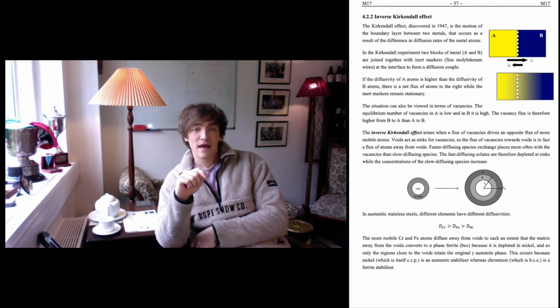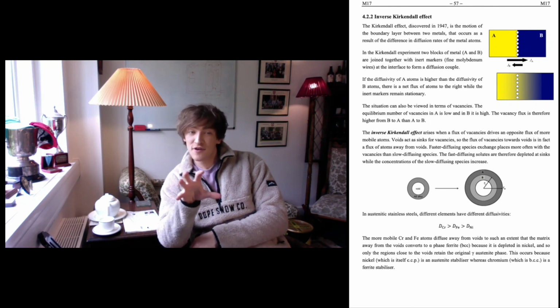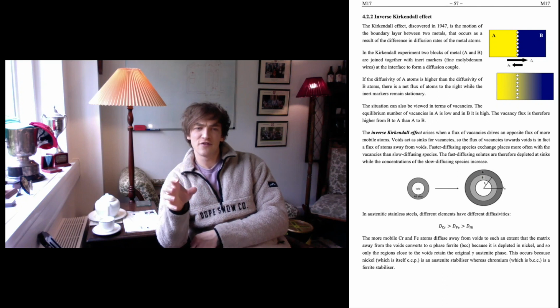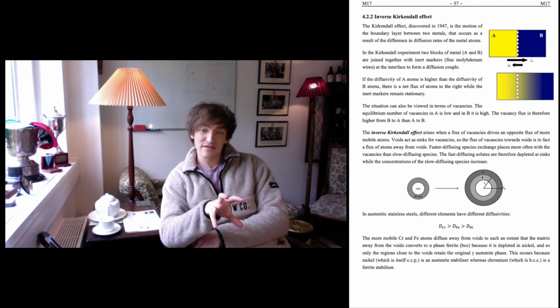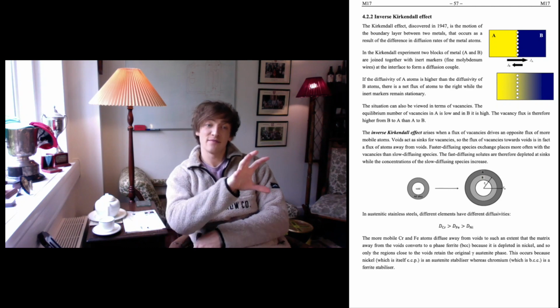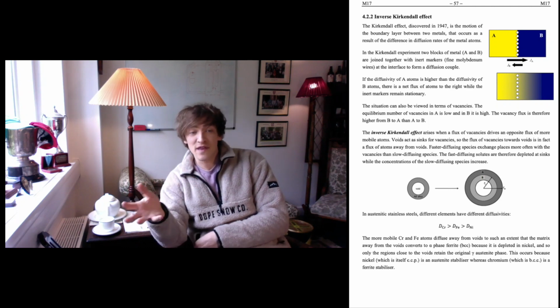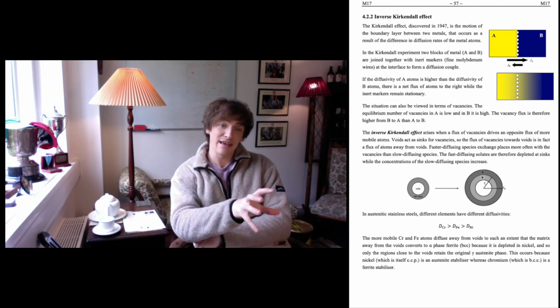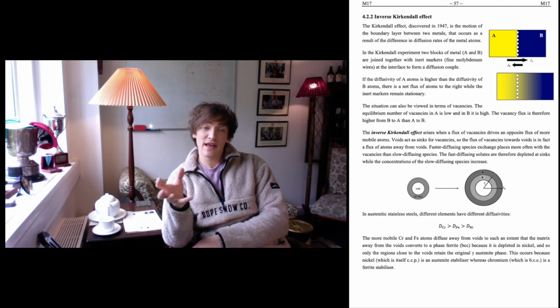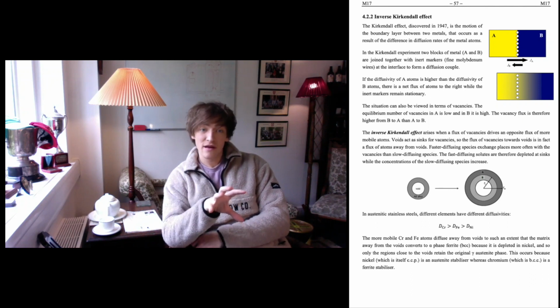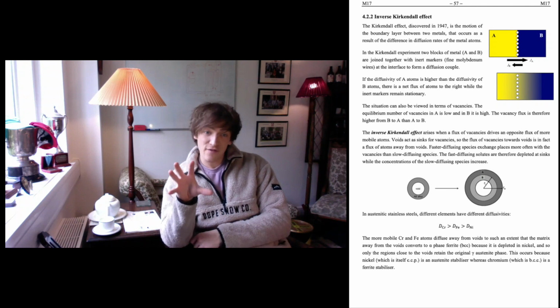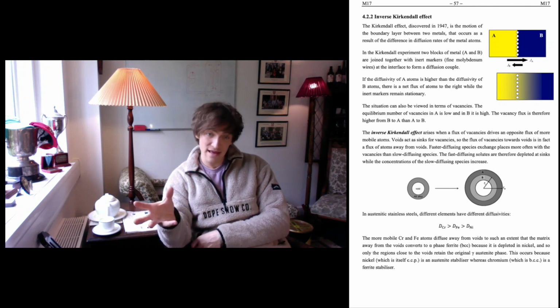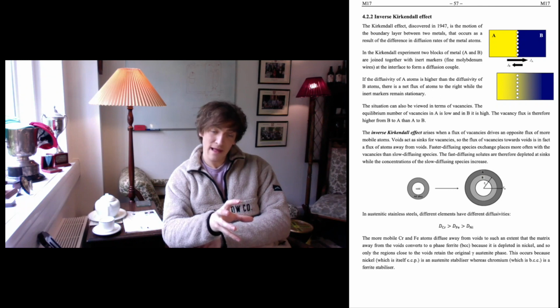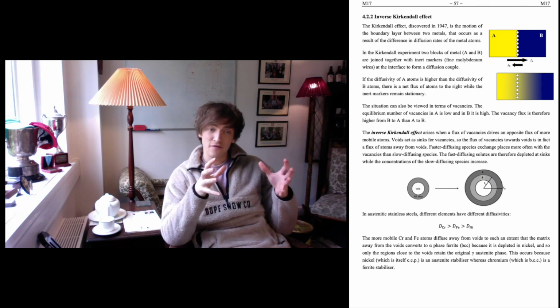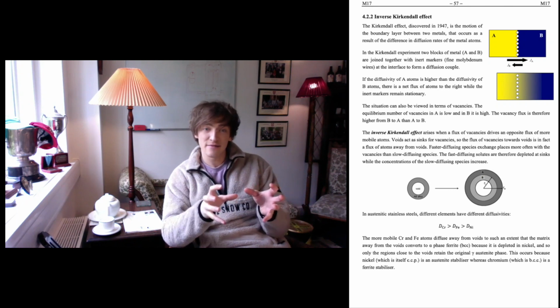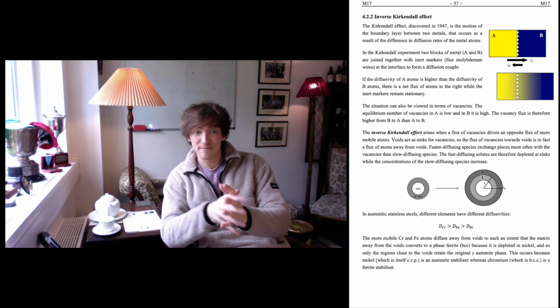Yeah? However, you can also view this, it might be easier, as being a net diffusion of vacancies in the opposite direction, rather than the atoms themselves. So the atoms A are mostly moving to B, but in order for that to happen, vacancies from B are moving to A. So in that case, the number of vacancies in metal A is low and is high in B. So the net flux of vacancies is from B to A. Okay? Yeah? The net flux of vacancies is from B to A, but the net flux of atoms is from A to B.